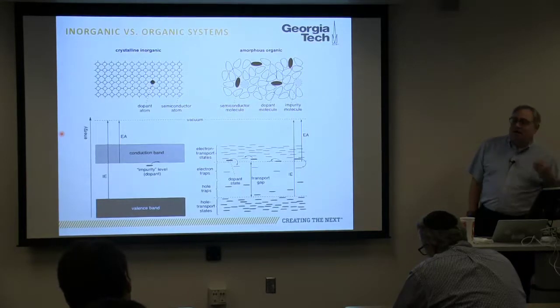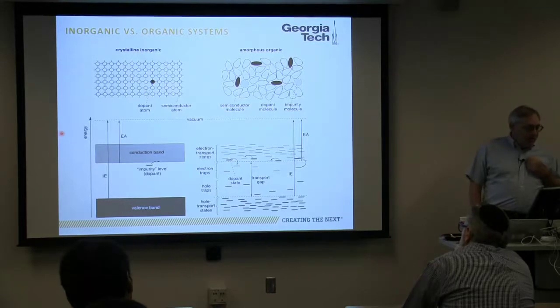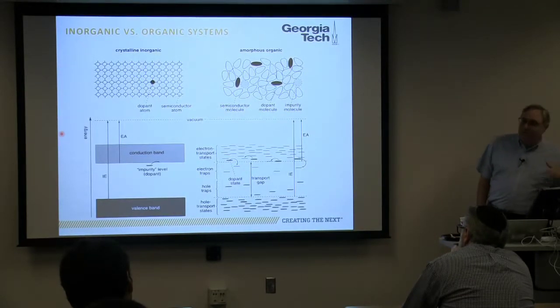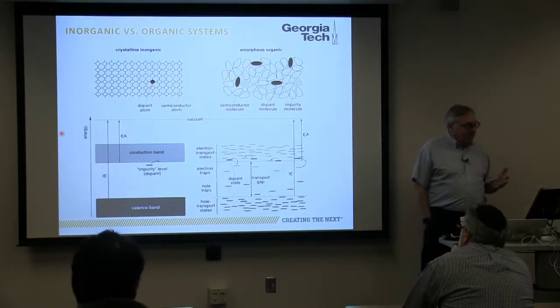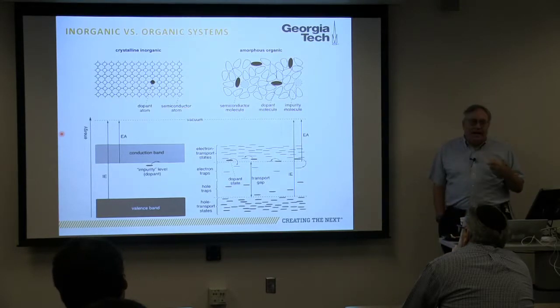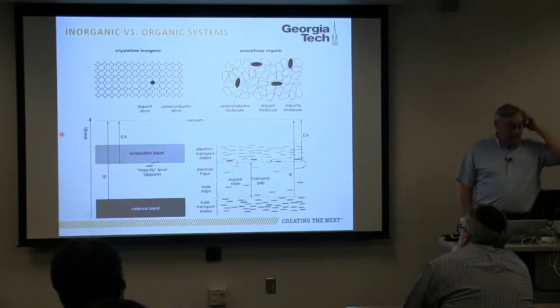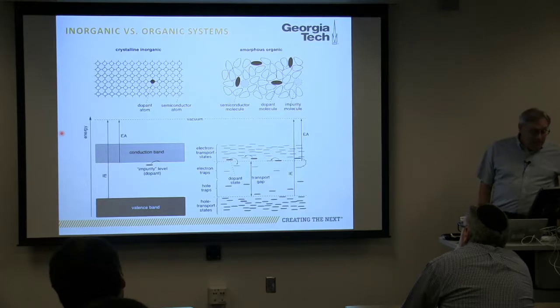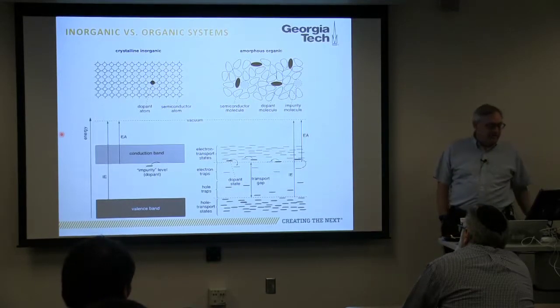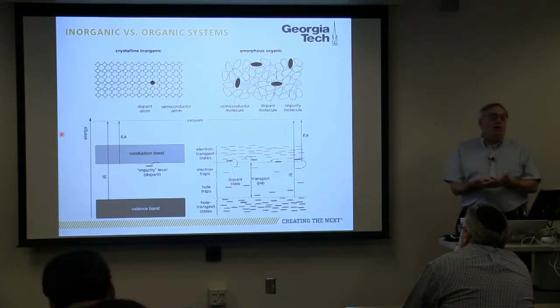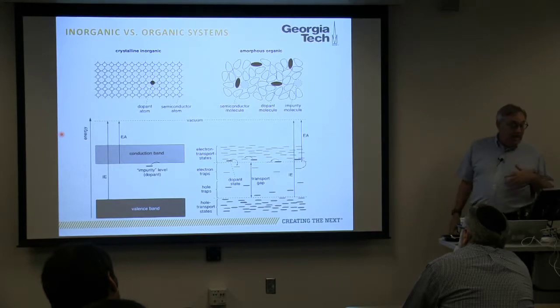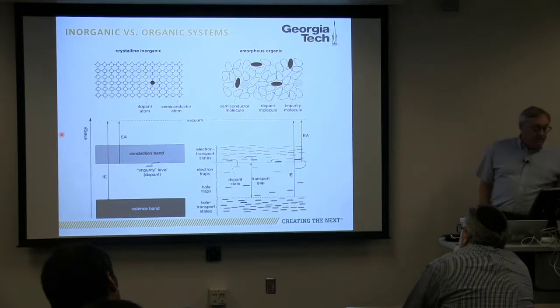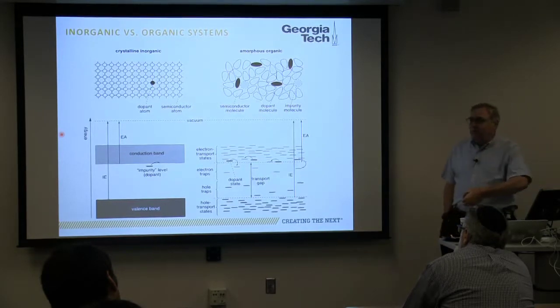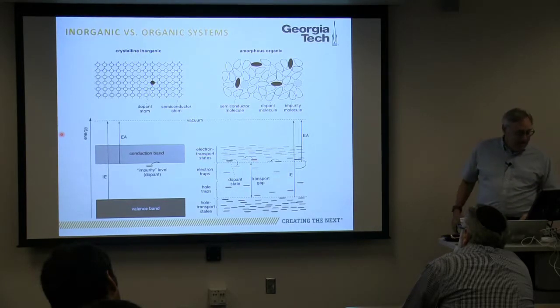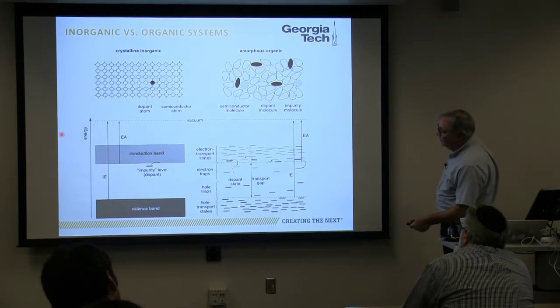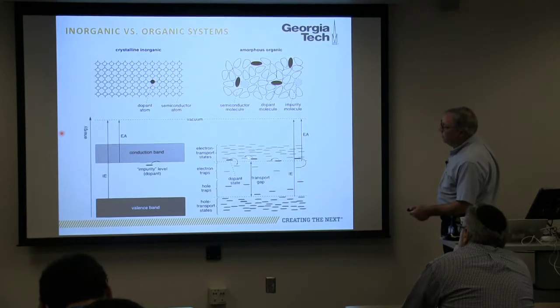And the way we think about the transport of materials in an organic system is somewhat different. In inorganic materials, we think about the conduction through valence bands and conduction bands. And in organic materials, people somehow use that language, but maybe not in the same way that people in the inorganic community use them. In particular, what we have is a manifold of localized transport states on either individual molecules or on segments of a polymer, and we can have gap states, as you can in an inorganic material, and when we dope, what we do is we take one electron out of a molecule that is in the whole manifold of states, and we can call that p-doping. And when we n-dope, we put an electron in here.